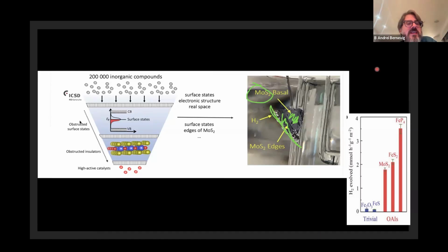The reason for this is that if I was to compute one of the topological integers of this material, it would tell me that the electron Wannier state has moved in between the atoms. Now, if it's moved in between the atoms and you cut a bond, i.e. make a surface, you can't cut through an atom because we can't split the nuclei. But you can certainly cut between the atoms by just taking a knife and cutting, or by splitting the material.